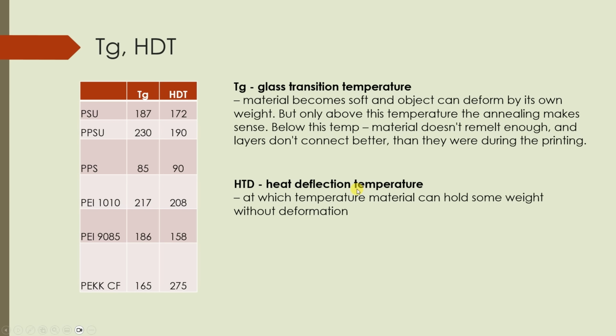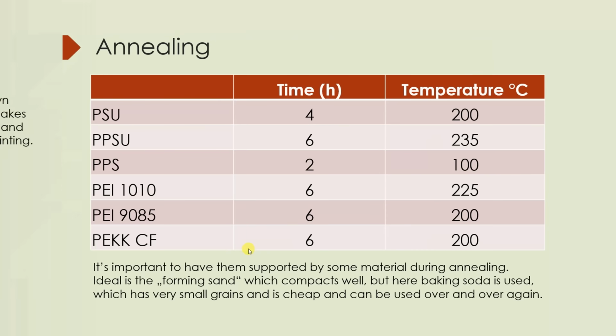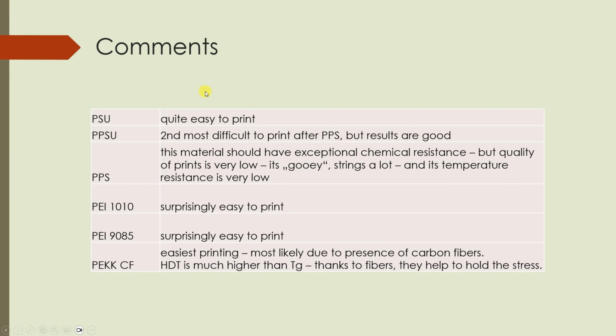And these are the glass transition temperatures, where the material becomes soft, and basically the annealing has to be done above this temperature. And HDT, heat deflection temperature, where the material can hold some weight without deformation. And these are the annealing information, the time and the temperatures, and it is important to have this material somehow supported during this annealing. The ideal is the forming sand, but here baking soda is used because it has very small grains, and it is cheap and it can be used several times. And these are just some comments by Pavel. The easiest for the printing was the PEKK-CF, probably because of these carbon fibers, and I have this experience with the regular materials too. The two hardest for the printing were the PPSU and the PPS materials.